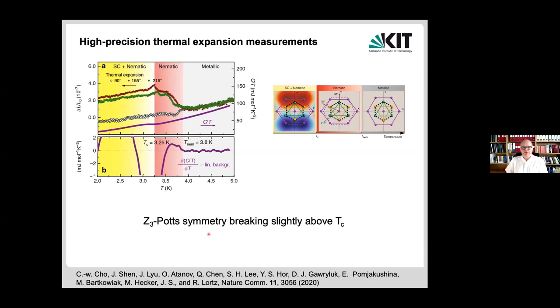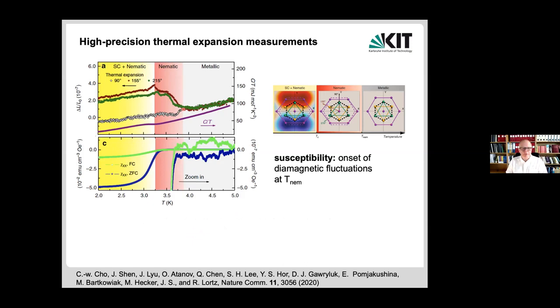So what we see is, yes, we have a Z3 symmetry breaking. We can call it Z3 Potts symmetry breaking. What would be cool is if we could really make a case that this is a fluctuation-induced effect. And then we discussed this quite a bit. And indeed, if you, for example, look at the diamagnetic response of the system, the susceptibility itself becomes diamagnetic in the superconducting state as it's supposed to be. But if you then zoom in, you see that the actual onset of diamagnetic fluctuations can already be seen at that upper transition temperature, which is precisely the one where you also see the symmetry breaking in the system